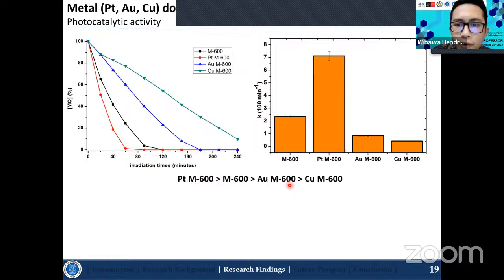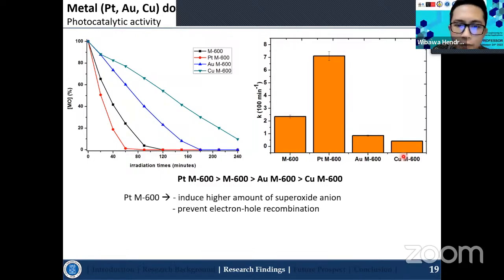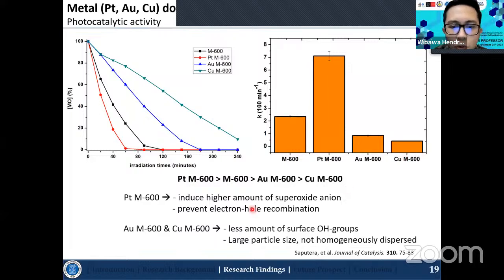And for the photocatalytic activity, we can see that by using the platinum dope on M600, or the composite which is calcined under 600 degrees C, it increased the activity for the methyl orange degradation up to around 3 times, compared with the M600. While for the gold and copper, it gives lower activity due to the smaller amount of surface hydroxyl groups, and also the particle size of the metal is too big, which can inhibit the catalytic efficiency of the mixtures of the TiO2 itself.